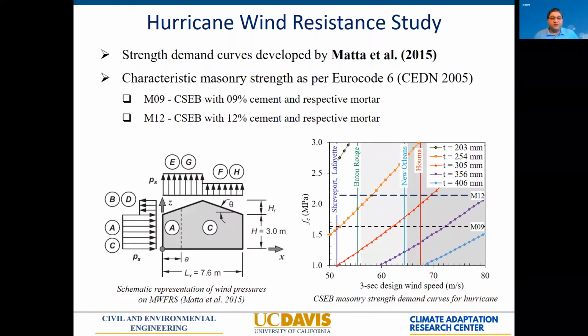We then investigated the strength to hurricane winds. I'm not going to describe this too much in detail, but this figure reports the curves corresponding to different thickness of the walls, so that on the horizontal axis you can read the design wind speed in meters per second at different locations, taken from ASCE 7. On the vertical axis, you have the characteristic strength of the masonry, with the two horizontal lines corresponding to the strengths of the blocks with 9% cement and the blocks with 12% cement.